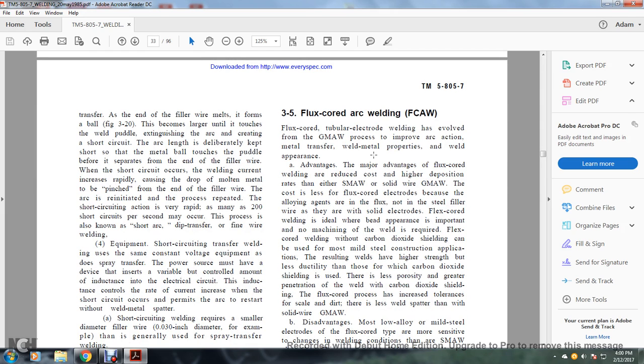As the end of the filler wire melts, a metal ball is formed, figure 3-20, and it becomes a larger unit until it touches the welded puddle, extinguishing the arc and creating a short circuit. The arc length is deliberately kept short so that the metal ball touches the puddle before it separates from the end of the filler wire. When the short circuit occurs, the welding current increases rapidly, causing the drop of molten metal to be pinched off from the end of the filler wire. The arc is reinitiated and the process repeats. The short-circuiting action is rapid, and as many as 200 short circuits per second may occur. This process is also known as short arc, dip transfer, or fine wire welding.